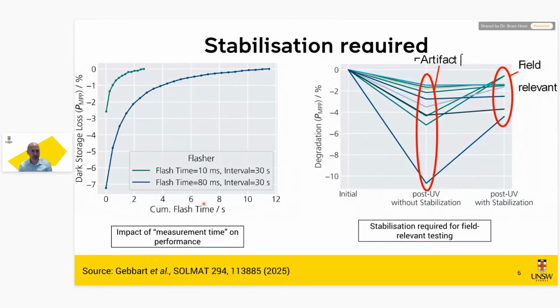Another insight that they showed is just by flashing them many times, you can get to a steady state value that is probably more representative of what you want to measure. But it also depends on the flash settings, and this was not fully explained in the paper, but that's something we're still working on to understand why there's such a difference between flash durations in this case.